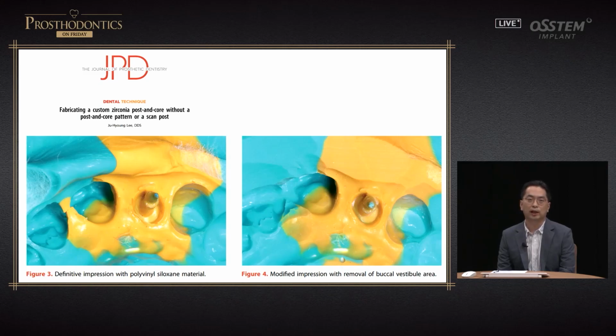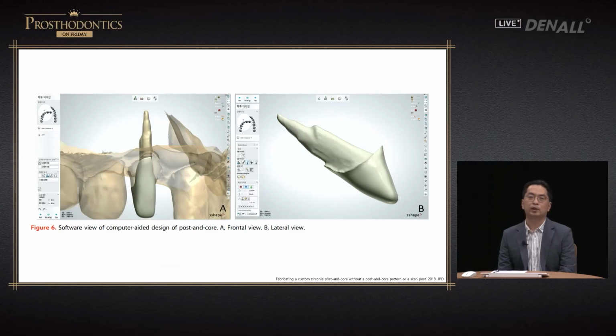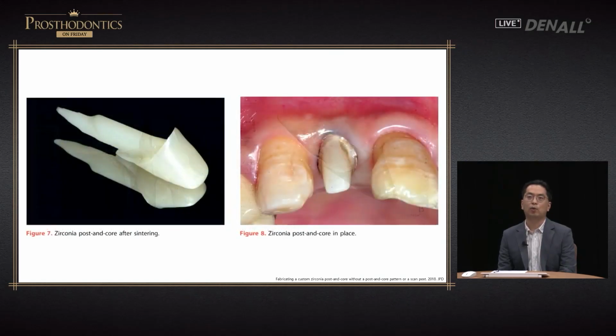In fabricating zirconia post, there are challenges in using oral scanner. The biggest issue is that the depth of oral scanner is not significant, therefore the deep inner surface of post could not be scanned. In general, as shown, you need to take impression of the post. The post needs to be scanned, the mesh needs to be reversed, and post and core needs to be designed and milled. That is the general way to do it. In order to do this, impression taking of the post was required.